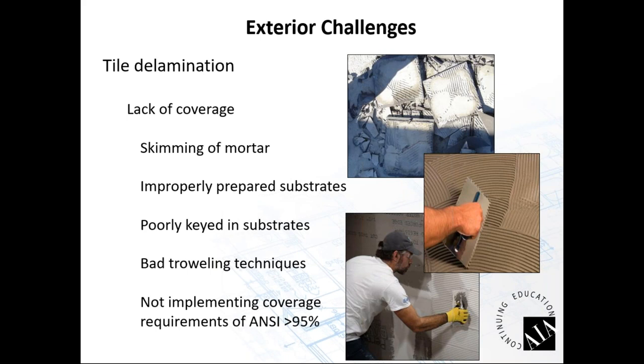Again, some of the challenges, and we've touched on this a little bit, is the lack of coverage. Make sure the mortar is properly covered. Watch for skimming of the mortar, and protect the area from wind, from draft, from the elements, so that the mortar doesn't start to have a skin on it, because the tile or stone will not properly bond into it. We currently are working on a project in Nebraska where the installer was going to be working on an exterior walkway of stone. And his concern was, this job was supposed to start in the summer, and with the heat that might be involved, how am I going to prevent this from skimming over?